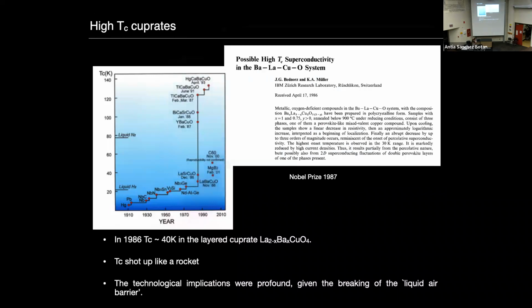But a big surprise came in 1986 when these two gentlemen, Bednorz and Müller, discovered the first copper oxide, or cuprate, superconductor. That first cuprate superconductor was the one that you see down here at the bottom, this lanthanum barium copper oxygen system. You can see that its Tc may not sound very high, 40 Kelvin, but again, in the context of the superconducting materials that we had up to that date, it was quite a big jump in a short period of time.